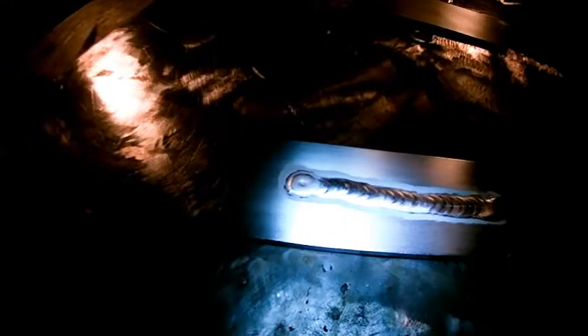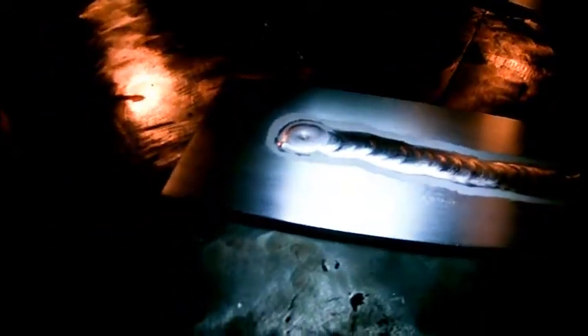Alright, there's our bead we just welded, and it looks pretty good. You can see the evenly spaced ripples. The crown is not too high. Puddle's a good size. And you see the white outline around the edges. That's where the cleaning has taken place.